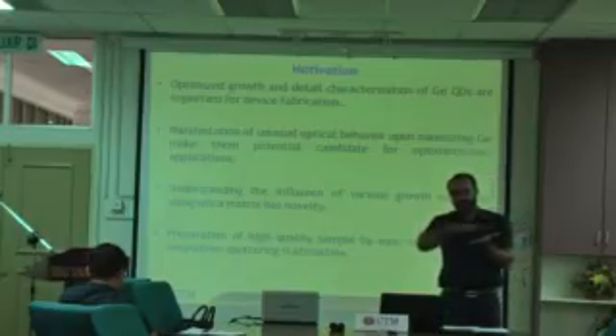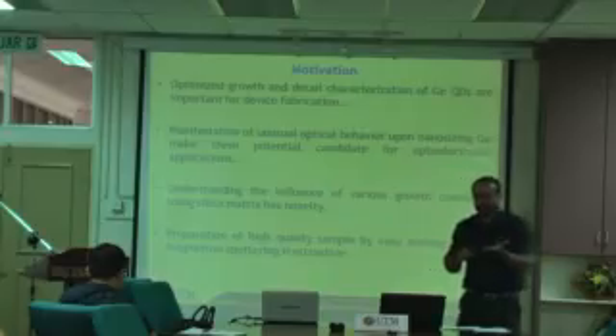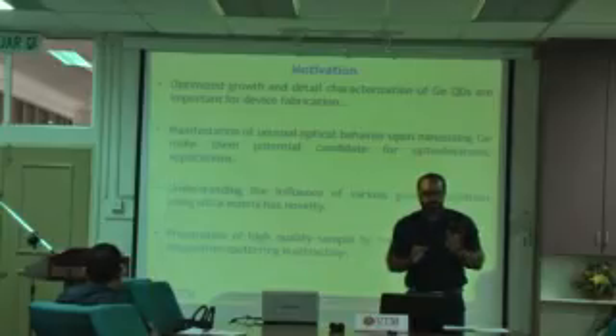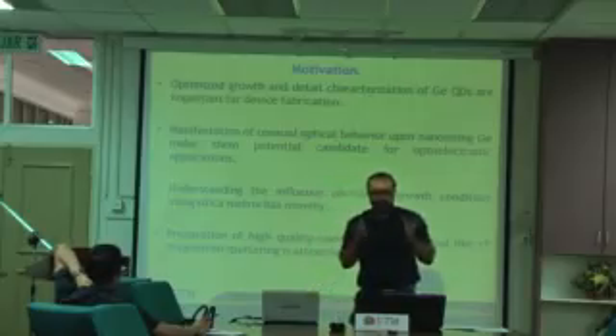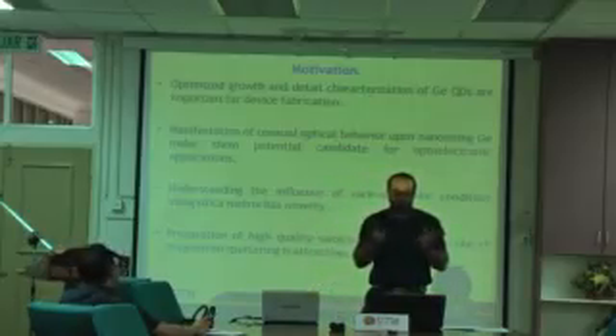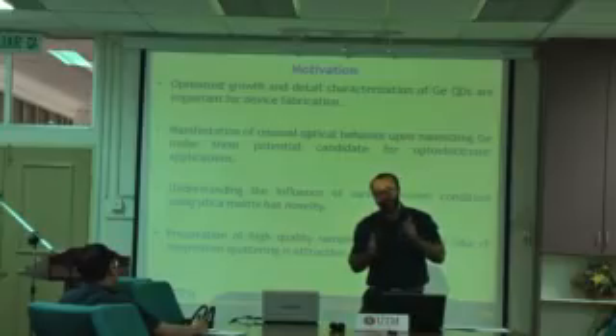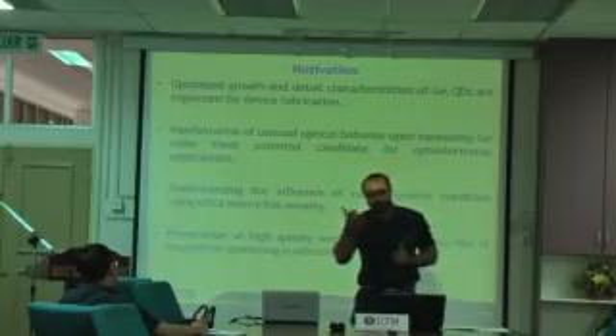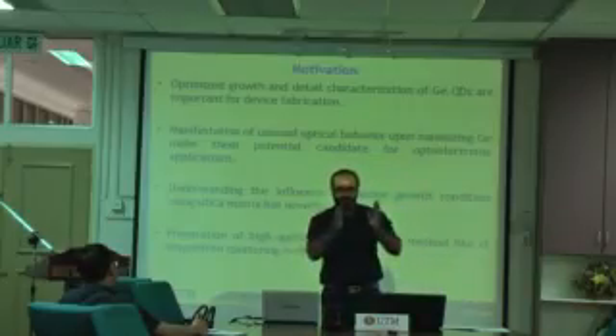That means islands can grow directly on the surface. It depends on the nature of the material and the lattice mismatch between the materials, so this is not in our control. For example, a lattice mismatch below 2 follows Frank-van der Merwe, above 4 follows Volmer-Weber, and between 2 and 4 follows Stranski-Krastanov.